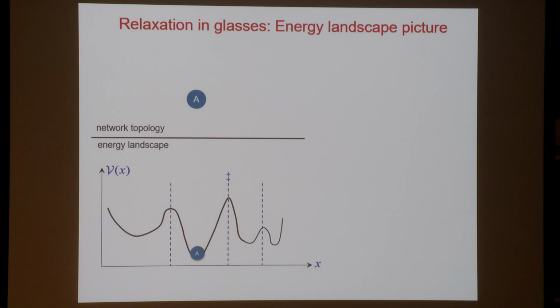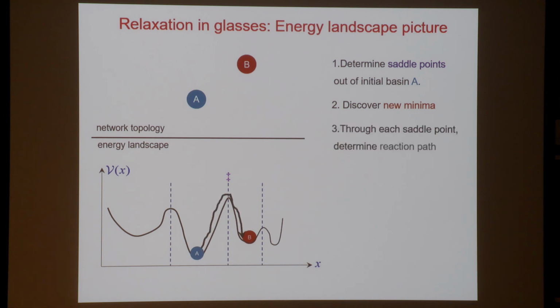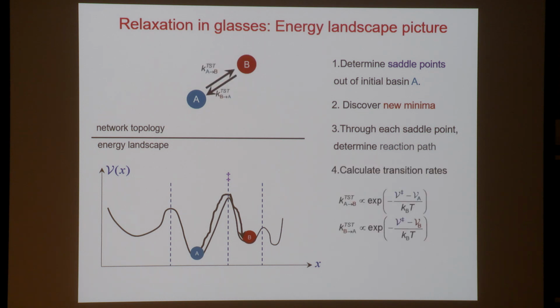What we can do is start from a minimum, and access as many saddle points as possible leading out of this minimum in the multidimensional configuration space of the glass. Having calculated such a saddle point, we can tumble down into an adjacent minimum by a steepest descent construction. So we can have trajectories which take us between adjacent minima, or reaction paths. And for each such reaction path, we can calculate through harmonic transition state theory rate constants for going from A to B and from B to A.